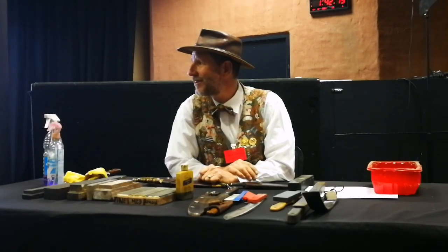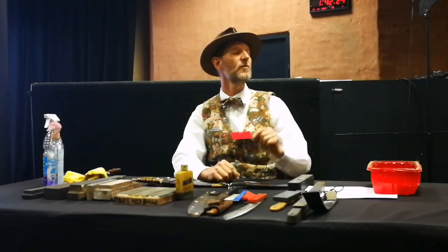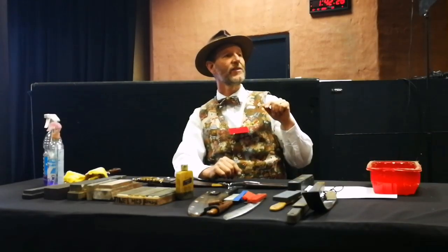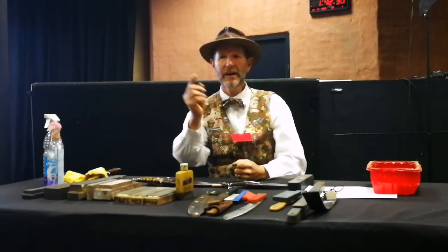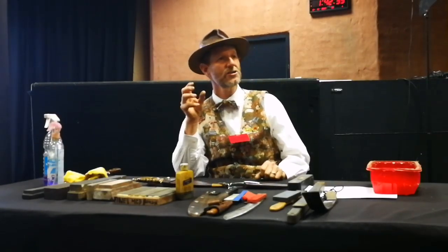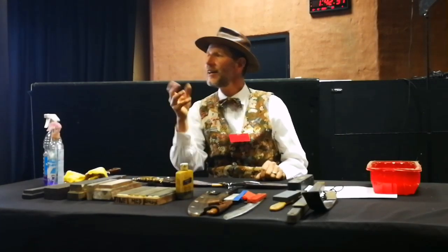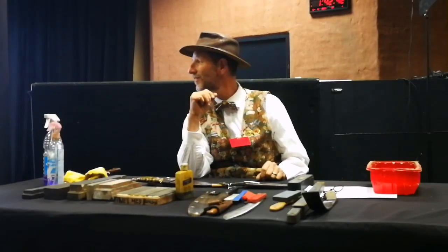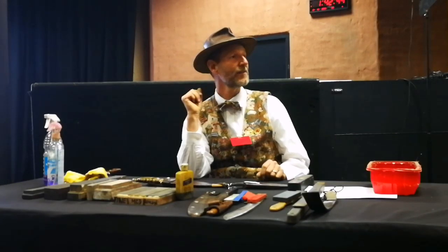But at the same time, steel will become blunt by chipping out if it's too hard. Abrasive resistance will increase the harder your steel gets, but to a point where the steel actually crumbles and fractures out. If you look at a cutting edge under a microscope that has been heat treated too hard, the edge doesn't roll or wrinkle or wear away, it actually chips out. So that's another way that a knife will blunt.